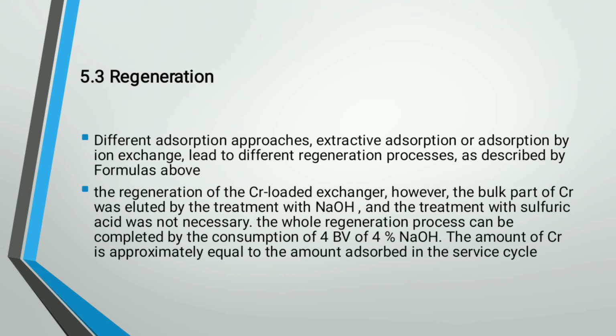And the following result is regeneration. Different adsorption approaches, extractive adsorption or adsorption by ion exchange, lead to different regeneration processes as described by the formulas above. For the regeneration of the Cr loaded exchanger, the bulk part of Cr was eluted by treatment with sodium hydroxide, and the treatment with sulfuric acid was not necessary. The whole regeneration process can be completed by the consumption of 4 BV of 4% sodium hydroxide. The amount of chromium is approximately equal to the amount adsorbed in the service cycle.